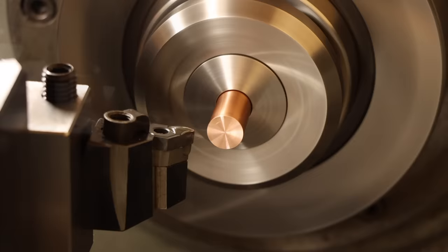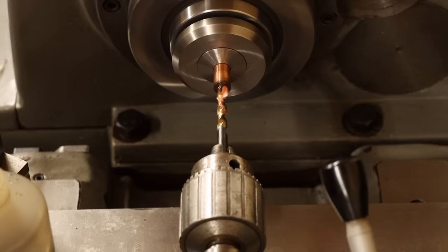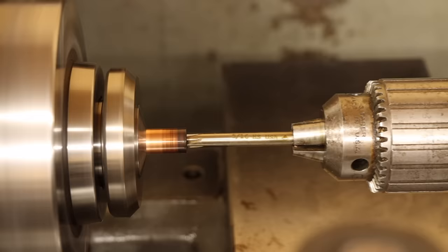That's way better. With a little more knowledge on how to treat this material, I'll dive into the bore. Keeping the drill well lubricated and regularly clearing the chips is apparently the name of the game for this copper. This bore will house the back end of the ink cartridge and will need to be a consistent internal diameter to allow the bolt to slide easily. So to achieve this, I'll finish the bore with a reamer, taking it to the final dimension of 5/16ths.